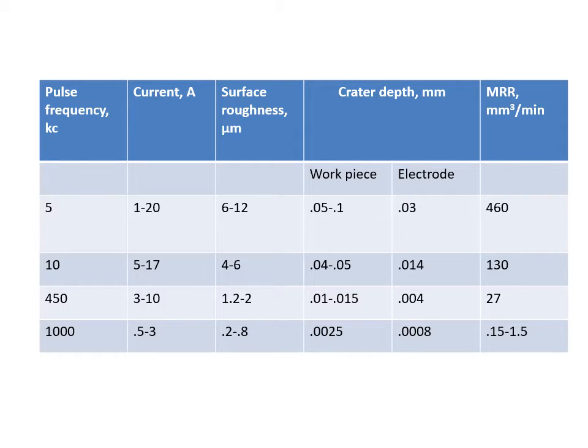The pulse frequency, for example 5 kc, requires a current in the range of 1 to 20 amps. Generally the surface roughness obtained is in the range of 6 to 12 microns, whereas the crater depth is in the range of 0.05 to 0.1 mm, and the crater depth formed on the electrode is in the range of 0.03. The material removal rate which can be achieved with respect to the workpiece is in the range of 460 millimeter cube per minute. Similarly, as I increase the pulse frequency, the current required goes on increasing.